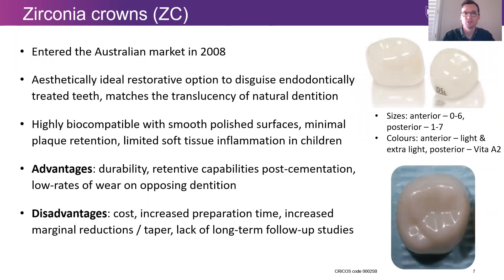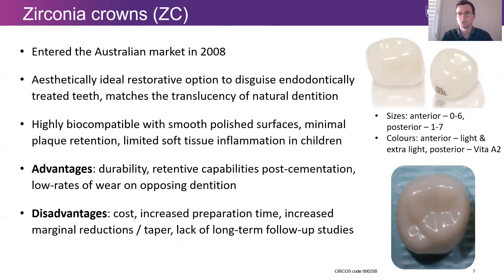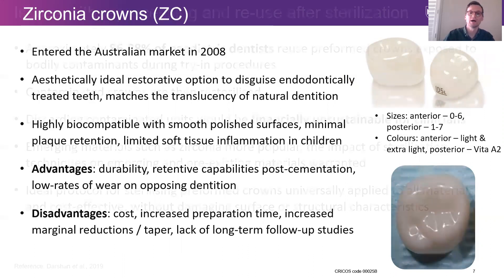Here we have the much newer zirconia crowns, which entered the Australian market in 2008. Aesthetically they're ideal for restoring or disguising endodontically treated teeth, as they match the translucency of the surrounding dentition. They're highly biocompatible with smooth polished surfaces, attracting minimal plaque retention as well as limited soft tissue inflammation. Their advantages are their durability, retentive capacity, and their low rates of wear on the opposing teeth. The disadvantages are their cost, increased preparation time, increased marginal reductions, and the lack of long-term follow-up studies.